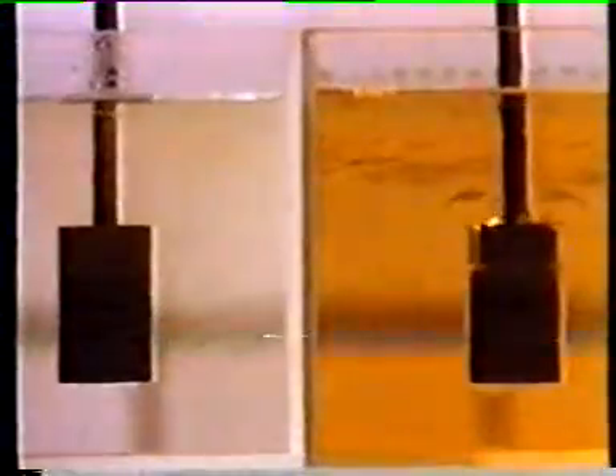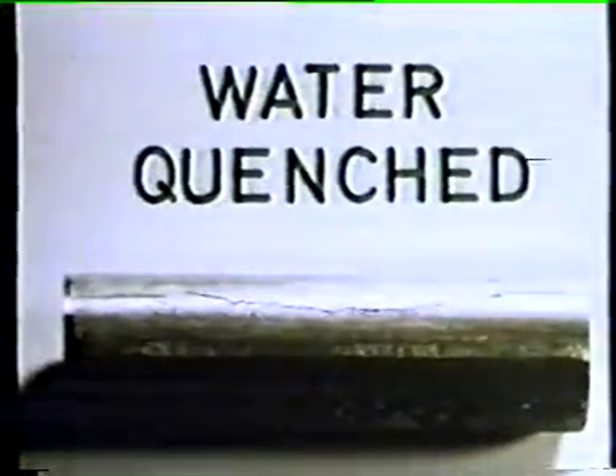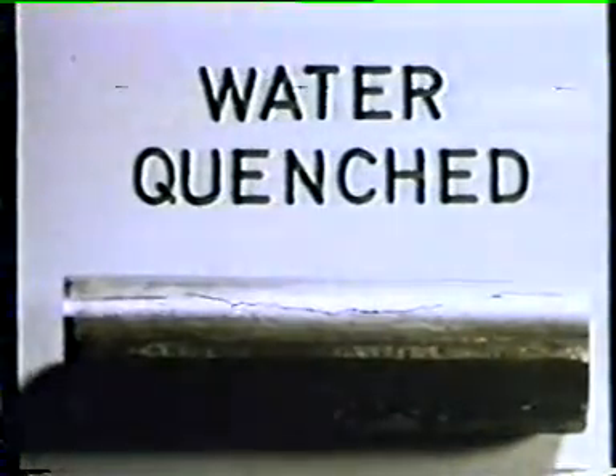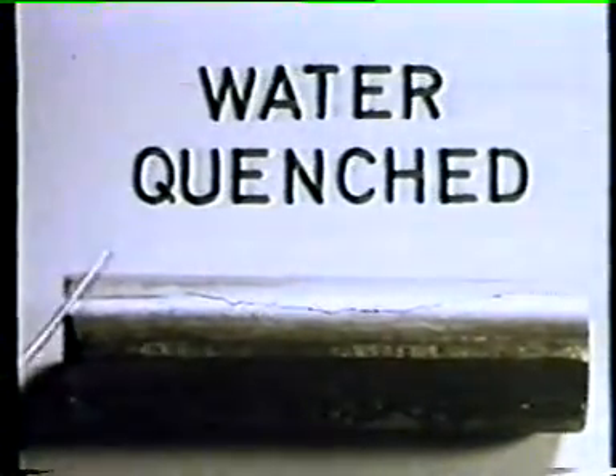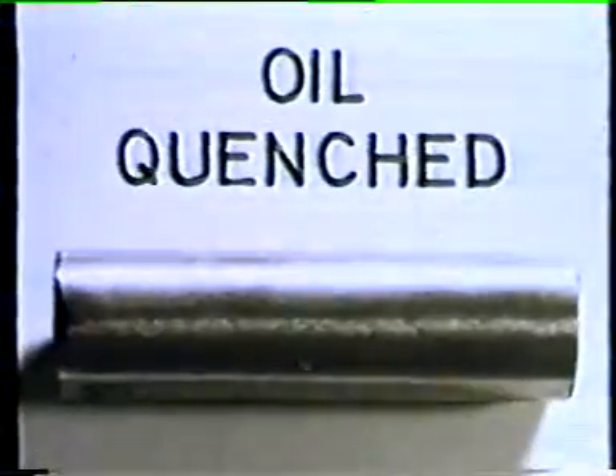So cooling in water is more rapid in the early stages and continues rapidly right down to 100 degrees centigrade. Since oil stops boiling at a higher temperature, cooling in oil is again slower during the final stage, when the steel actually hardens and when stresses may occur. Here is a section of steel after quenching in water. It shows numerous cracks which weaken the structure, the result of rapid quenching, which may also distort the metal. The same steel after slower quenching in oil shows no cracks or distortions.